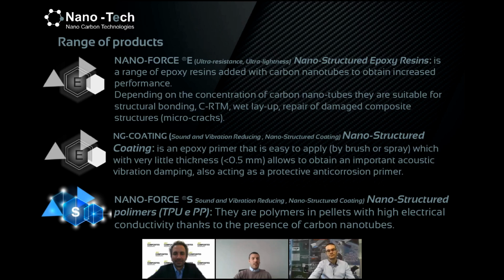We have a multifunctional coating, the NG-COATING, that is an epoxy primer, easy to apply, that has the possibility to damp vibration. So it's useful for light structures in order to have corrosion protection and a lightweight solution to dampen vibration.